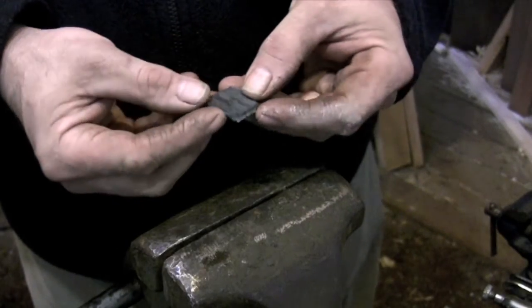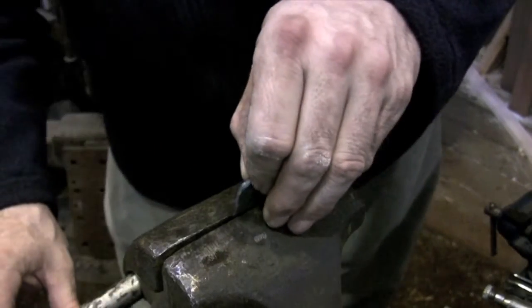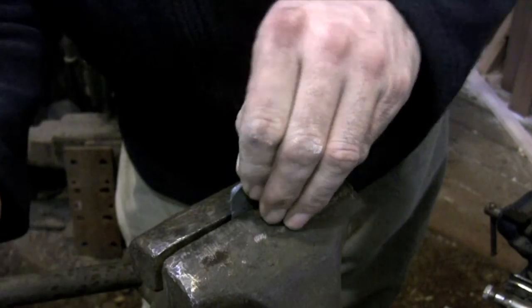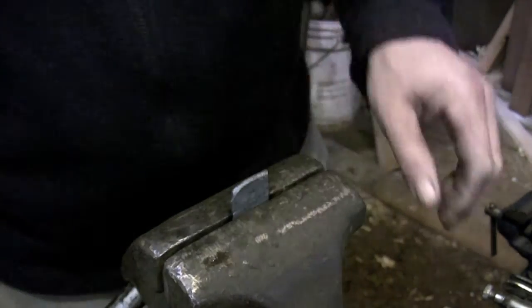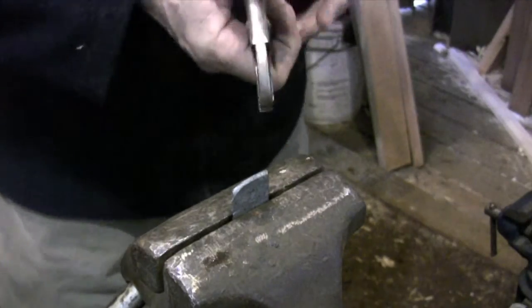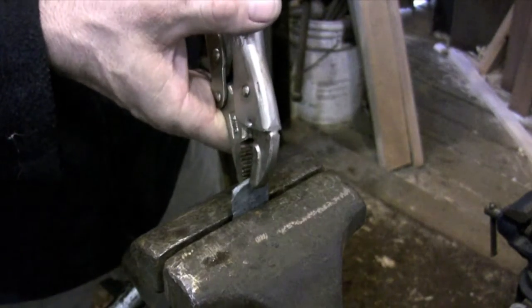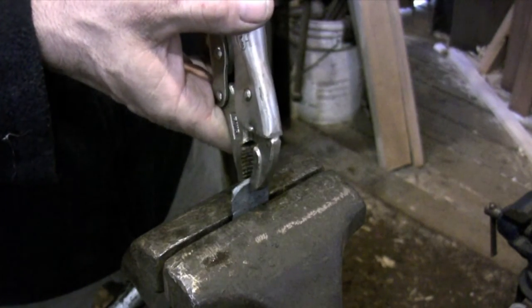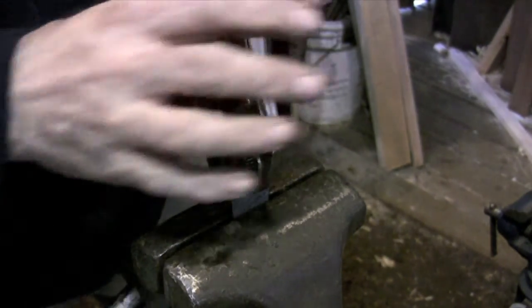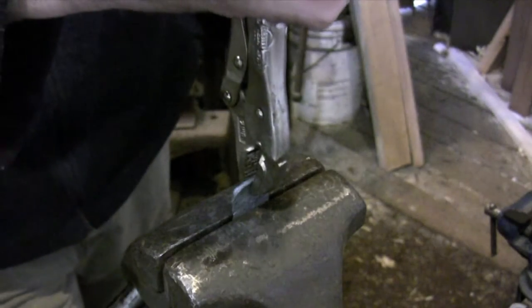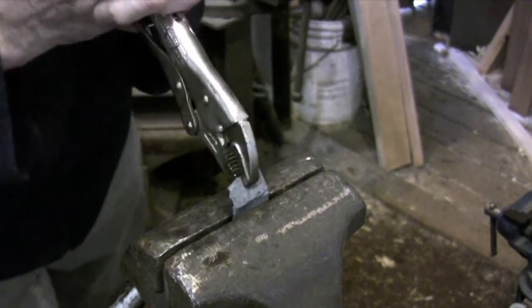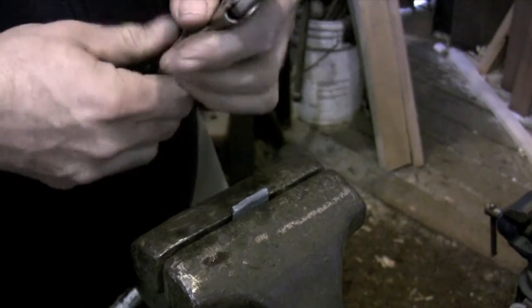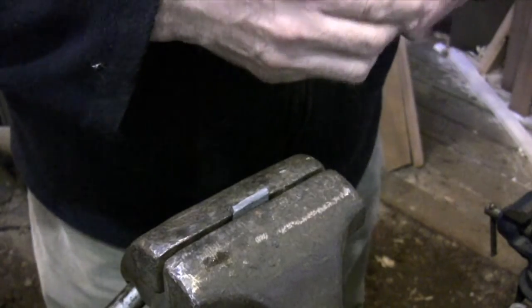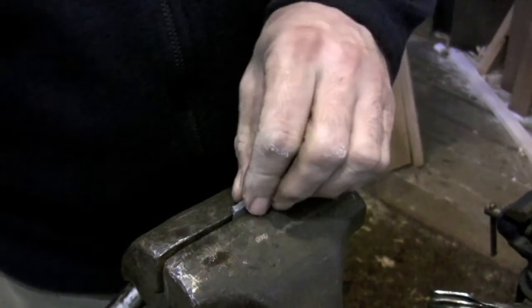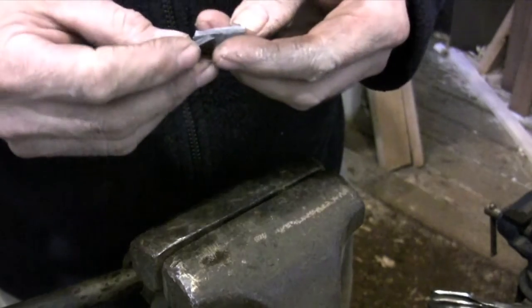So now that I have my three test pieces, I can place them in the vise and try to break them along that weld line. The first one that I'll be testing is the first sample with only one forge weld. And as you can see, it doesn't take much pressure to break this weld once we're able to apply pressure directly to the weld joint. The interior surfaces are clean, there's no contamination, it just didn't have time to mature into a proper weld.